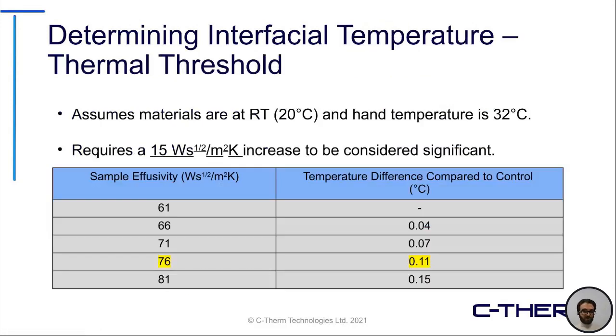Well, if we run through the equation that we showed earlier, we're assuming a few things here, that the materials are at a room temperature of, let's say, 20 degrees, and your hand temperature is at 32. With those numbers, if you run through the equations and you have these example effusivity values, so one sample, that base control, was, say, 61 effusivity, sample 2 was 66, and so on and so forth. At which point does that difference become detectable or significant? So if we use the idea that a decrease in temperature of 0.11 degrees is a detectable difference by the human hand, then we can show that you would need an effusivity difference of about 15 watt second to the 1/2 meter squared Kelvin to be noticeable.